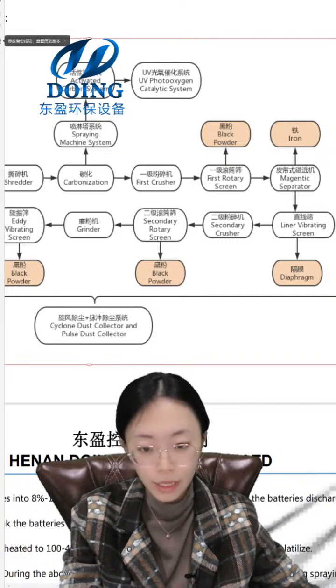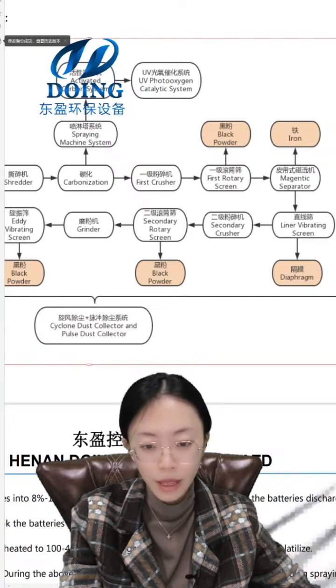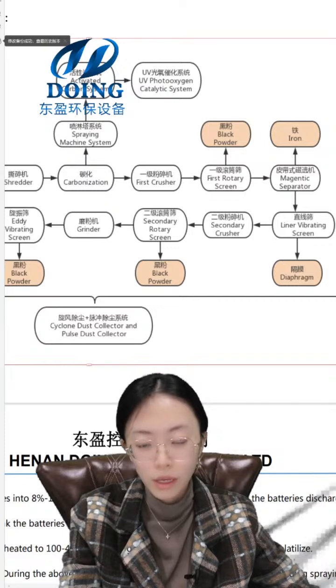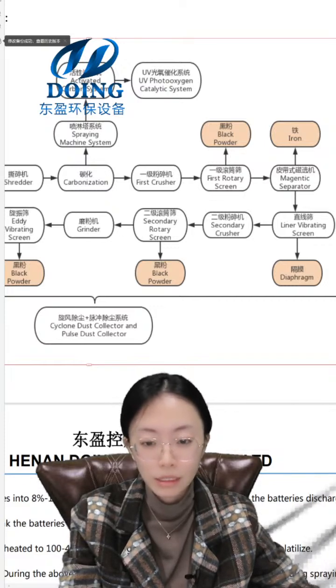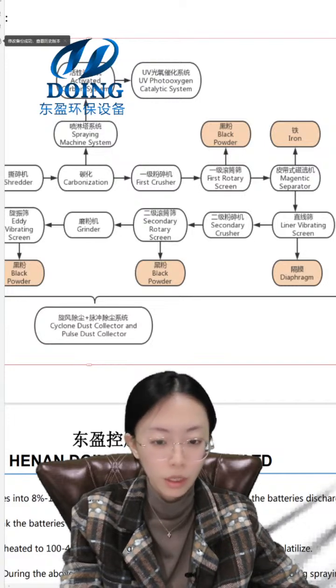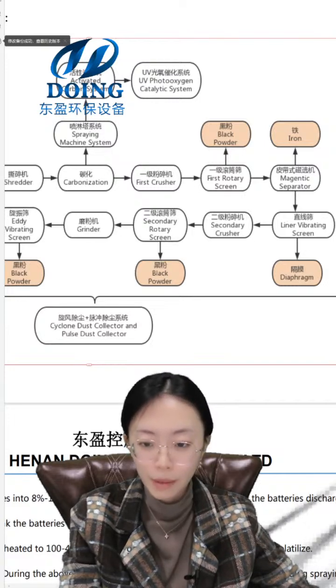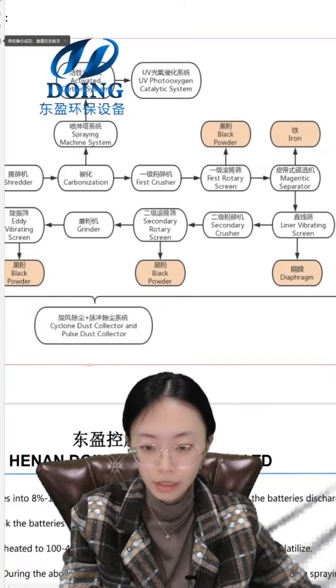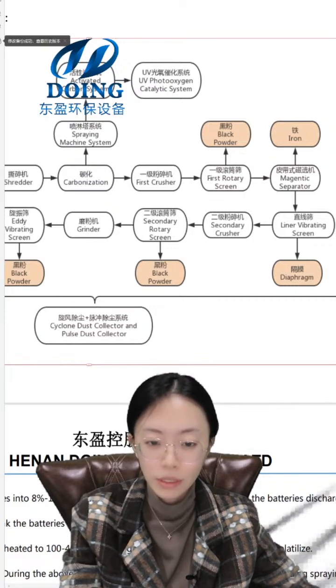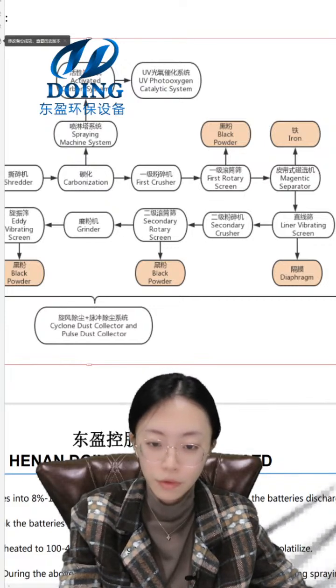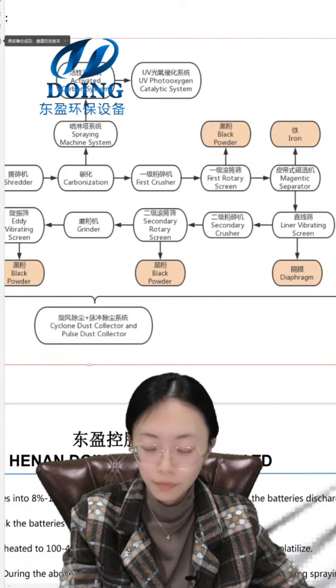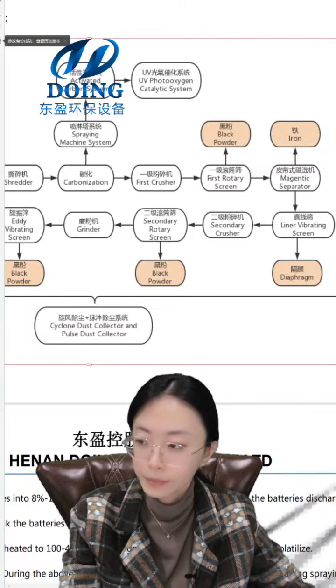And they have 3 layers. The top layer of the screen is the diaphragm. It is equipped with pipes and fans, a removal system to remove the plastic diaphragm. And the middle layer is the copper, aluminium, and black powder. And the bottom layer is also the black powder. So in this step, the recovery rate of the diaphragm is about 98%.